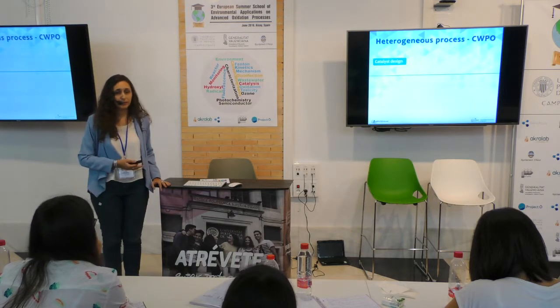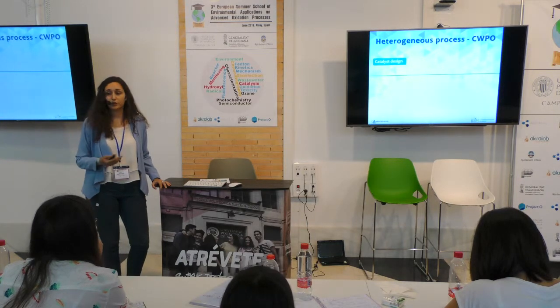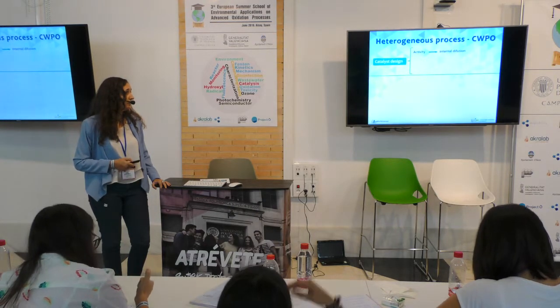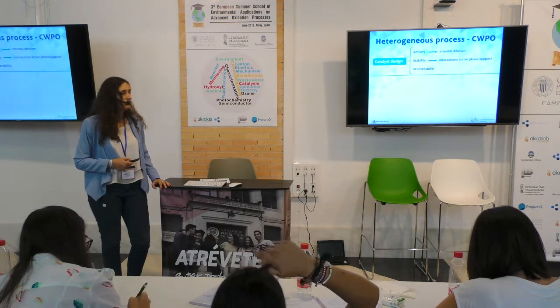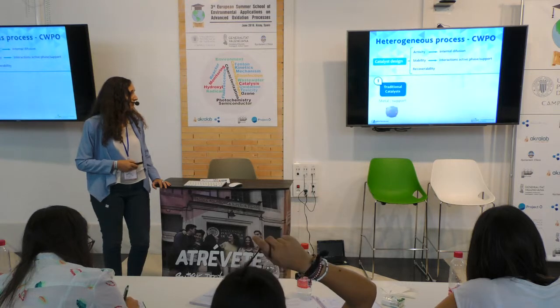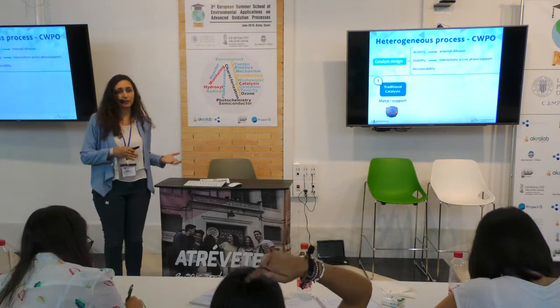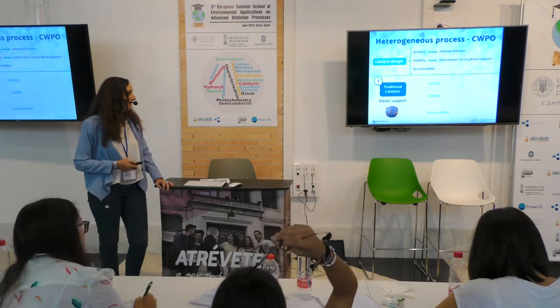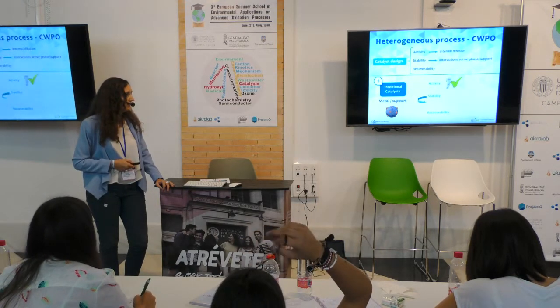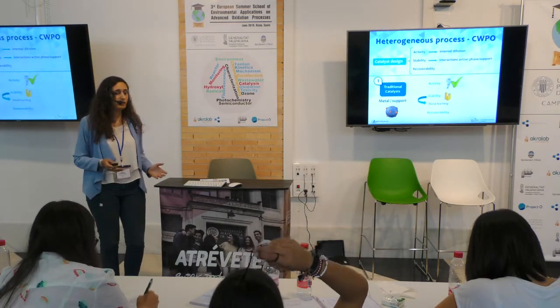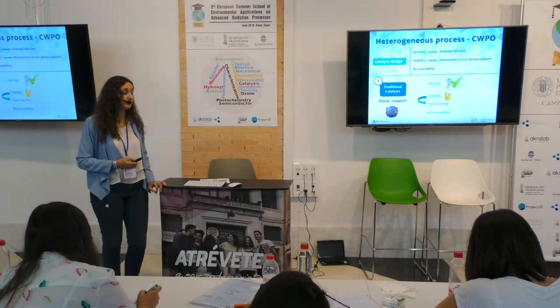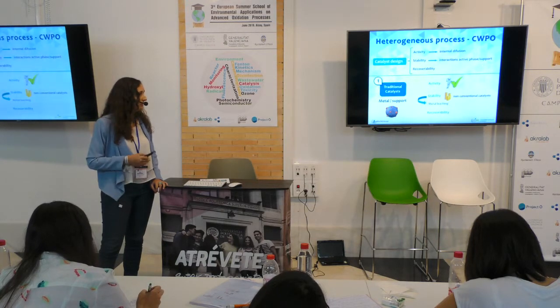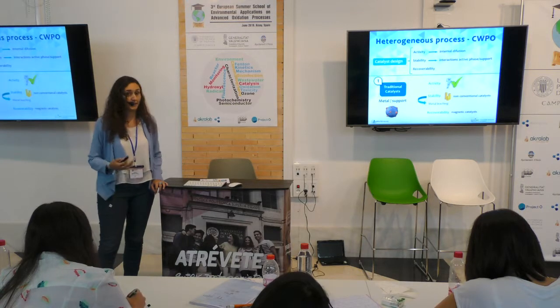Due to this disadvantage, most authors have worked on developing a heterogeneous process for catalytic wet peroxide oxidation. In catalyst design, we have to consider activity, stability, and recoverability. The traditional catalyst would be a metal immobilized on a support — activated carbon, alumina, zeolites — and these materials have very high activity. But stability is very limited due to metal leaching, making our catalyst expensive. To overcome this drawback, we have non-conventional catalysts. In terms of recoverability, we have magnetic catalysts. The non-conventional catalysts include iron-bearing minerals or residues such as goethite, hematite, magnetite, and iron tailings, as well as carbon materials from amorphous to more ordered forms.